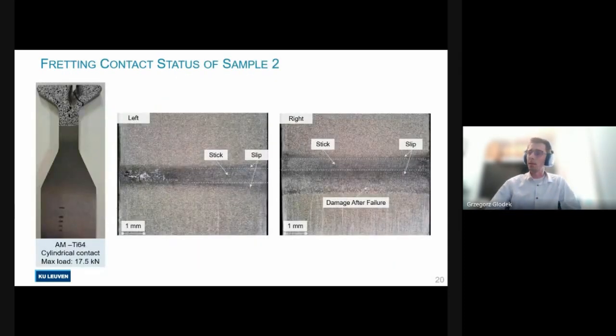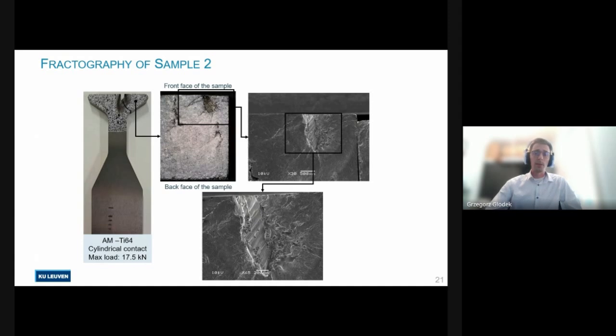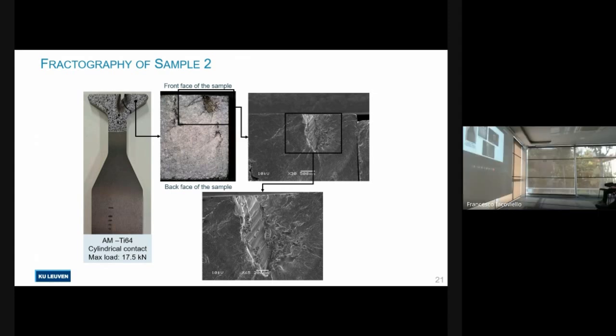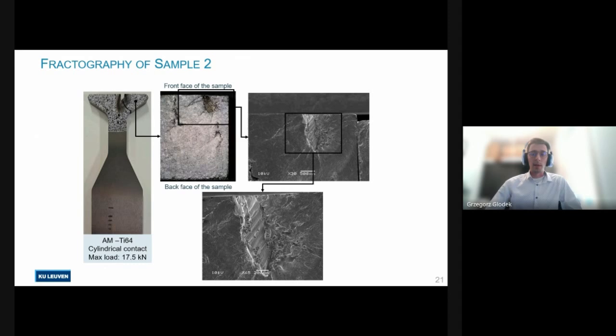Now, as I said, a number of AM samples failed outside contact, like this one, which failed at the transition zone between the curvature and the flat portion. Further analysis revealed that the presence of a large internal defect, which acted as a stress concentration, caused this early failure due to plain fatigue. The globular particles you can see here are likely particles of unmelted powder and point to the origin of the defect as a lack of fusion defect.